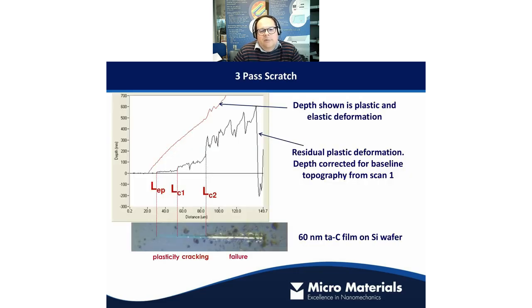Well, this is an example of a 3-pass scratch test. It's a thin tetrahedral amorphous carbon film on a silicon wafer that we're looking at here. What we've done is a 3-pass scratch test. For the first scan, we scan along our intended scratch path with a low contact load. Maybe we'd use something like 0.1 of a millinewton to just produce a topography of our initial sample surface.